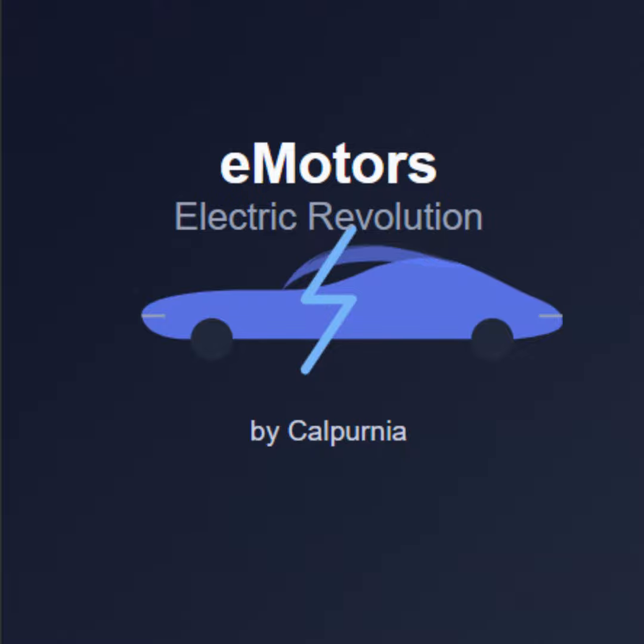It's important, though, to mention the exception here. LFP batteries, that's lithium iron phosphate. If your vehicle uses LFP chemistry, which is becoming increasingly popular, especially in standard range models. Like some Teslas and Fords now. Exactly. LFP cells are inherently much more robust at high states of charge. They don't suffer the same level of stress near 100% as NMC cells do. So generally, LFP batteries are much happier being charged to 100% regularly. That 20-80 rule doesn't really apply in the same way. Good clarification.